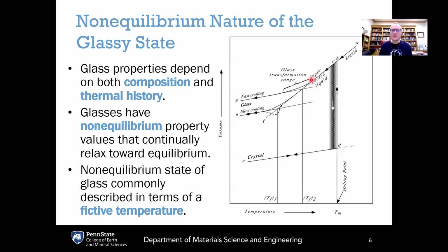And when that happens, this is what's called the glass transition or the glass transformation. Now, this is not a phase transition that occurs at a particular temperature. Rather, this is a kinetic transition that represents a gradual freezing in of the supercooled liquid structure, as it simply takes too much time to be able to have configurational changes in that liquid. And with that gradual glass transformation process, we get a gradual freezing in of this disordered supercooled liquid structure into the glassy state.